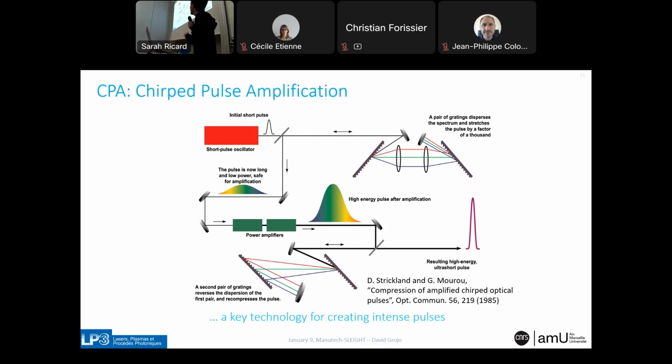It consists in the fact that to bring femtosecond laser pulses to high energy without damaging the amplifying medium, you first need to stretch the pulse with a grating pair. Then you can amplify this long pulse and recompress it with another grating pair. So you understand that at the output of all the lasers we use, we have a grating pair that we can use to pre-compensate GVD for laser material processing experiments.